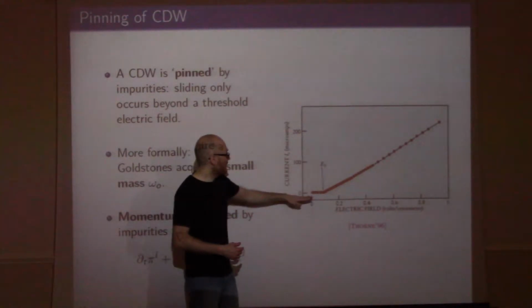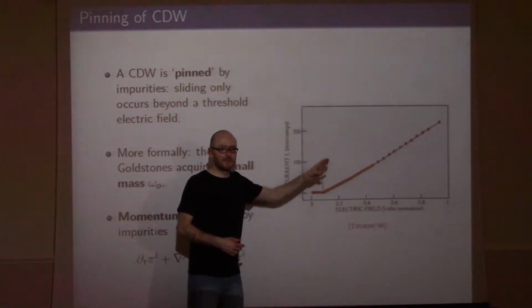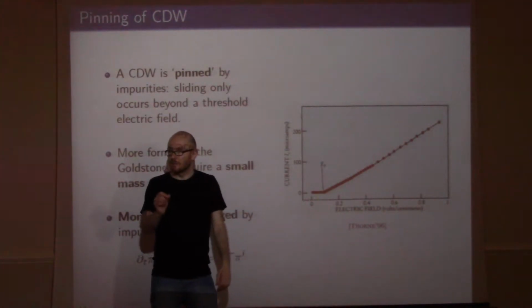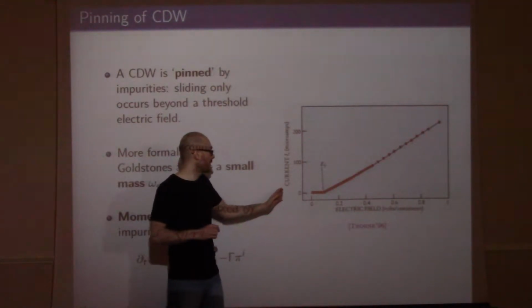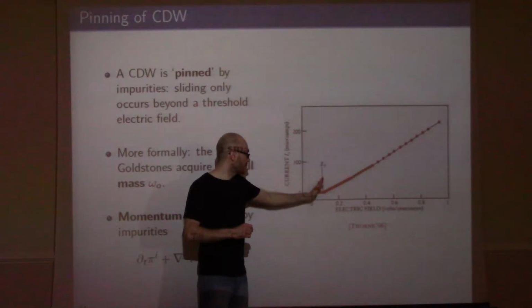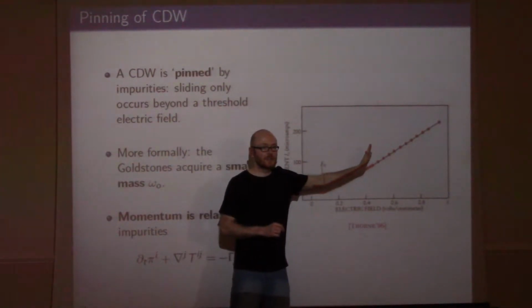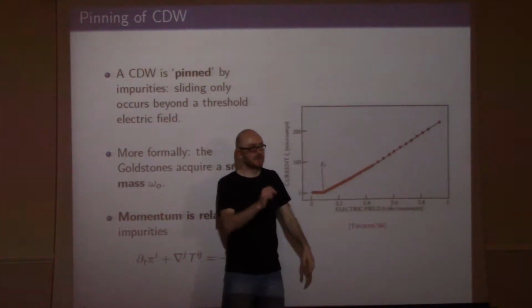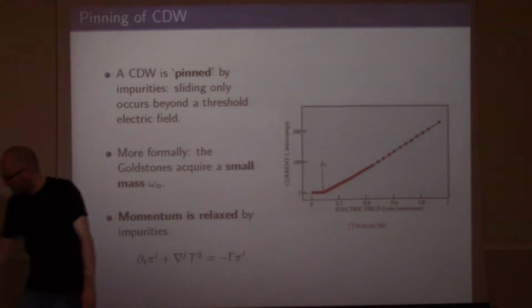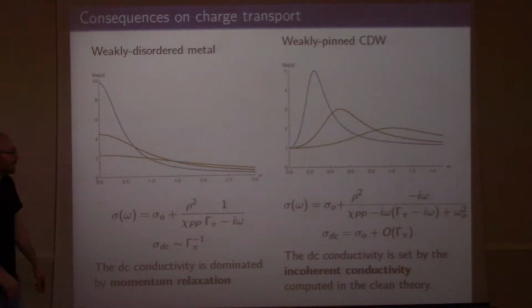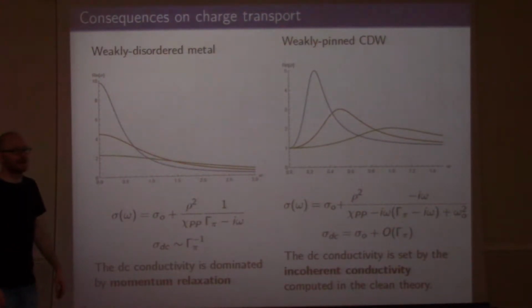And typically what would happen is that the charge density wave would get pinned by this explicit breaking, by disorder. So typically when you apply an electric field, there's some threshold electric field before the charge density wave starts moving, because otherwise it gets pinned. To understand a little bit better, we can look at what the formulae are.